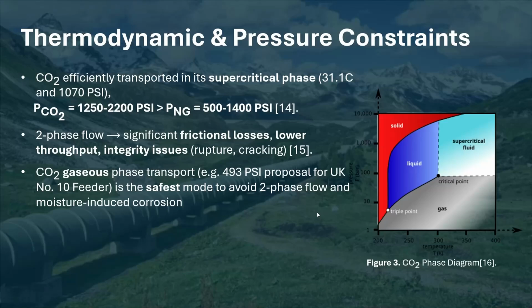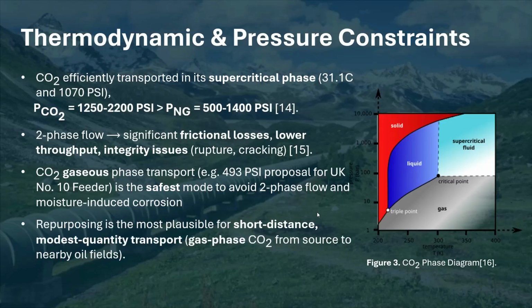From some of the examples I showed before, the CO2 is generally transported in the gaseous phase, which is meant to be the safest route in order to avoid two-phase flow, where we can operate these lines within the design limit of these pipes and also avoid some of those integrity issues that I mentioned. So repurposing seems to be more plausible for short distance and modest quantity transport.